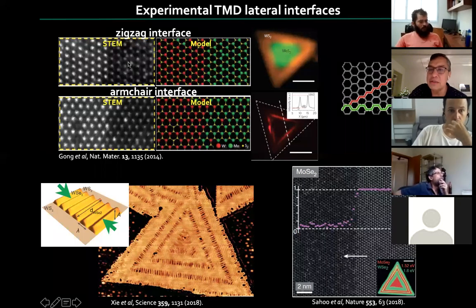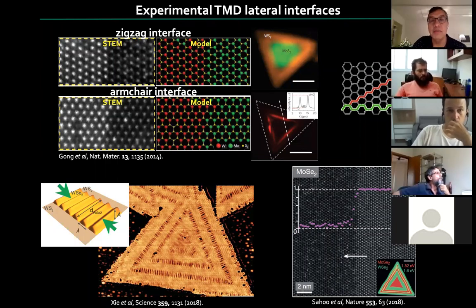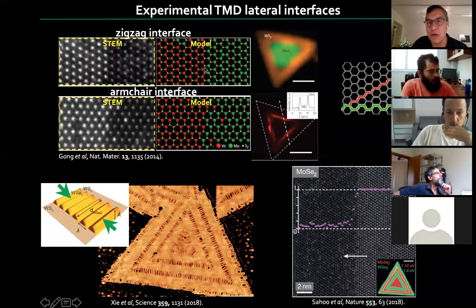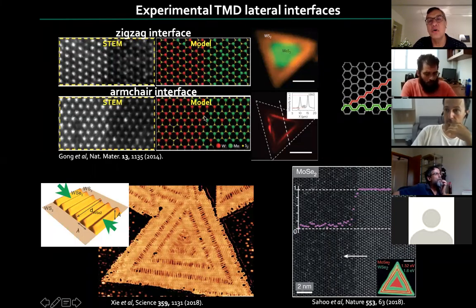And that's important because the size of the lattice constant, rather, is mostly determined by the chalcogen atom. And so when you change metal across an interface like this, you change the lattice constant, but only slightly, so there is relatively little strain. And of course, you can have different orientations, so-called zigzag, you can see here, or an armchair, depending on where the crystallite is grown.